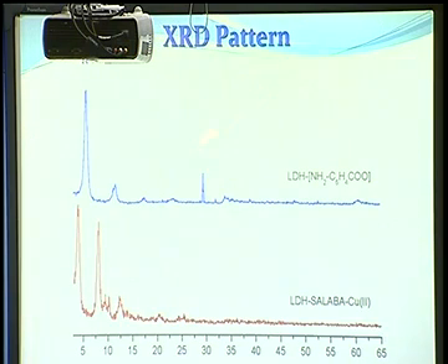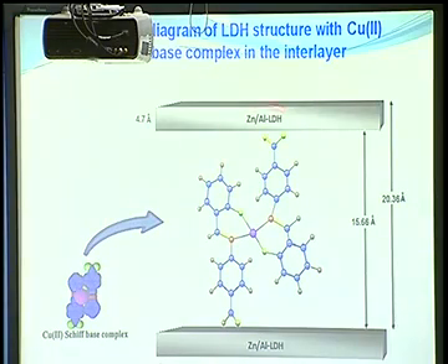This is the XRD pattern. First one is of support and the second one is of catalyst. It is having spacing 15.68 angstrom along the 003 plane, and it increases to 20.36 angstrom in the catalyst. This is the schematic diagram of LDH structure, in which this copper complex is inserted into the layer of this layered double hydroxide, and the increase in spacing indicates successful intercalation of this complex inside the layer of this support.